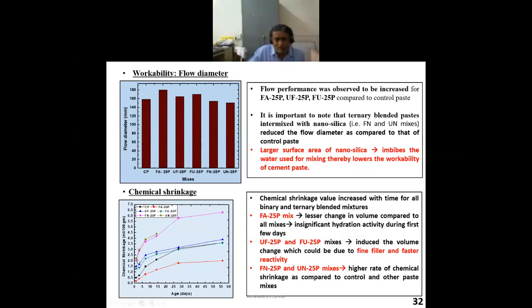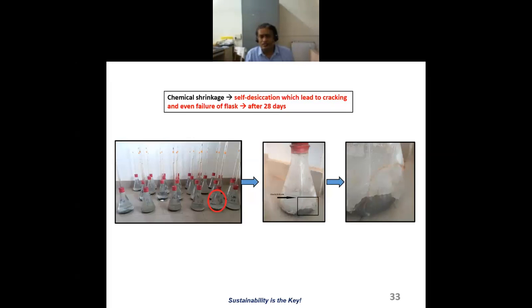Now, see here in one of the mixes, the topmost mix, that is UN25, the ultrafine fly ash nanoparticle mix. After 14 days, you can see there are no results reported, meaning the test could not be done. The beaker in which the chemical shrinkage measurement was being done got broken because of the faster reactivity and higher rate of chemical shrinkage. Now I will show you the picture. We call this phenomenon self-desiccation, which leads to cracking and even failure of the flask.